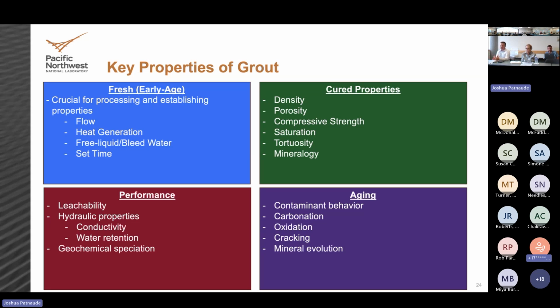So what we try to do is study and screen our grout materials in the laboratory in reasonable time frames in our leachability tests. There's a number of them. We then take promising materials, do longer tests on them so we can understand their longer-term evolution, do those longer-term tests in representative conditions, and take very promising things and put them in more of a realistic field environment.